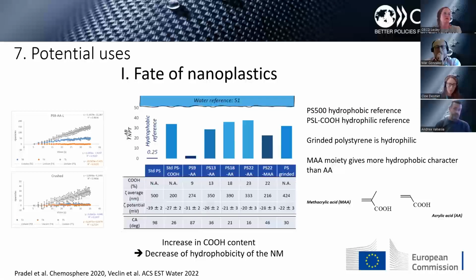Here we quantify the hydrophobicity of the different nanoplastics. In the bar chart, the closer the bar is to the reference with water, the higher is the hydrophilicity. So the smaller the bar, the more hydrophobic the material. We can note that the two different moieties give different hydrophobicity character to the nanomaterial, and the hydrophobicity degree of the particle decreases with the carboxyl content.